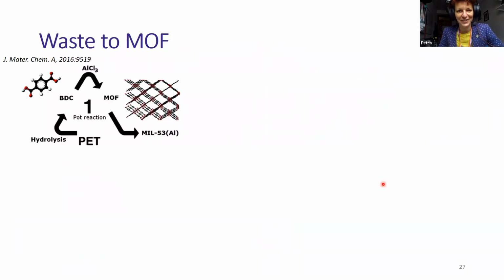And finally, and again, unfortunately, I don't have a lot of time for it, but with many of the metal organic frameworks using terephthalic acid as a linker, polyethylene terephthalate or PET plastic is one of the interesting linker sources that could be used. Now, this has been coined a while ago, but I would just like to point out that in this case, of course, you have aluminum chloride, in which the inorganic node is just the cation. So it's very easy, well, relatively easy to use just single cations as inorganic nodes for the assembly of frameworks in a sustainable way, because of course you don't have to worry about assembling polynuclear species.